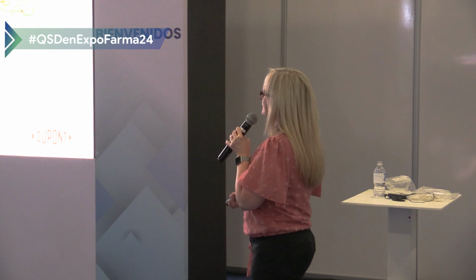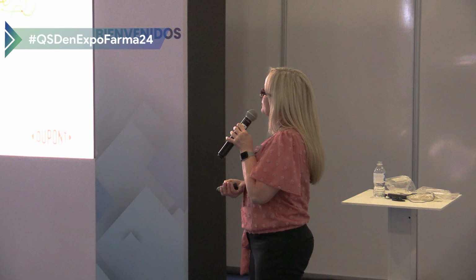So a little bit of the basic chemistry for a soft skin adhesive. It has two different parts. It's a part A and a part B. Again, it's 100% silicone. And the part A is basically a polymer with a platinum catalyst to induce the chemical reaction. And then part B is base polymer with cross-linker. So you mix these two parts together in equal ratios and it begins to cure. And it's a very lightly cross-linked material.